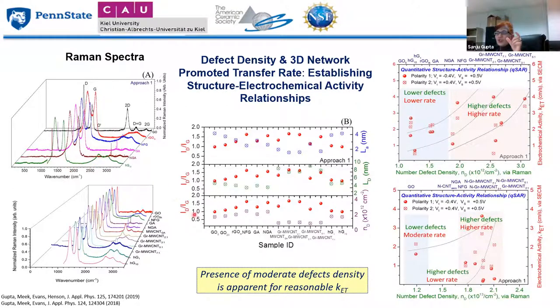And then you take the intensity ratio of the D to G band, and what we can determine is the defect density. And we establish the defect density versus the electrochemical activity, or electron transfer rate, the same k_ET coefficient that I showed you before. And we establish what we call these quantitative relationships. And we can see that you require a moderate amount of defects in order to have a better electrochemical activity.